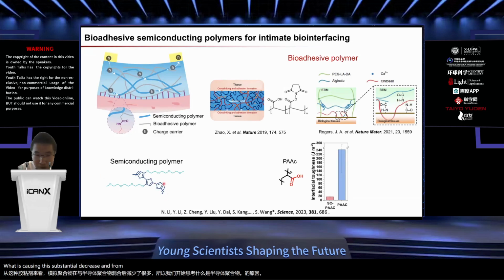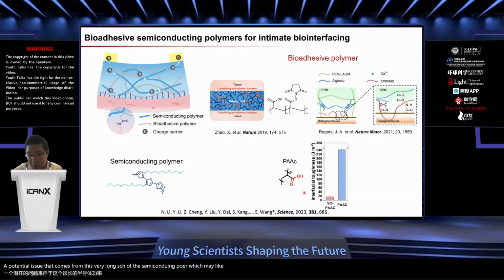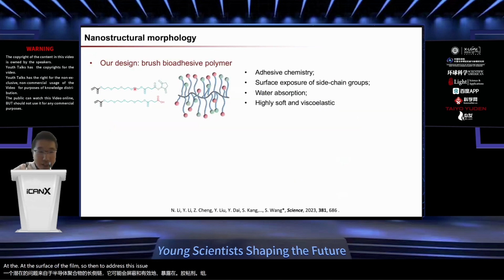From looking at this polymer structure closer, my student Nandi noticed a potential issue that comes from the very long side chain of the semiconducting polymer, which may screen and shield the effective exposure of the adhesive group at the surface of the film. So to address this issue, he designed a structure that significantly extends the length of the side chain so that it can enable the effective exposure of the adhesive group. So we call it a brush adhesive polymer.